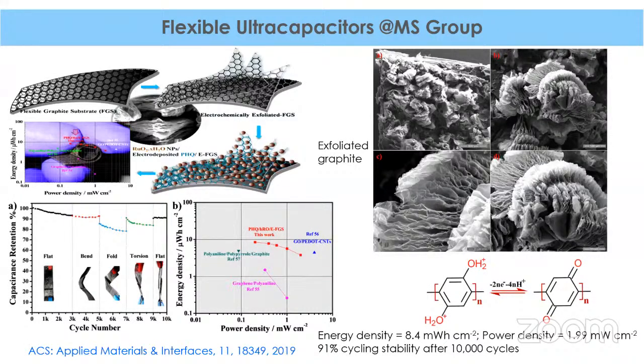In that case, again a PDMS base, polydimethylsiloxane, was used, and graphite flakes were coated on this PDMS substrate, and then this substrate was electrochemically exfoliated. Because PDMS is non-conducting, only the graphite gets exfoliated into graphene oxide-like sheets. Here you can see it; we call it the flexible graphite substrate. This is a direct transformation of graphite to few-layer graphene, because we are not making graphite oxide first, as is usually done in Hummers' method, where we first synthesize GO and then reduce it. Here graphite has been directly electrochemically exfoliated into graphene sheets like this.